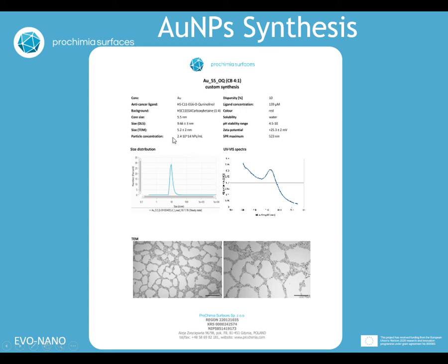And again, the size of the gold nanoparticles this time was from TEM measurements about 5.2 nanometers, and the size obtained from the hydrodynamic measurements from DLS is about 10 nanometers, so definitely it's larger than the metallic core, which provides information that we have attached the ligands to the surface. And the ligand concentration was estimated at around 140 micromolar.